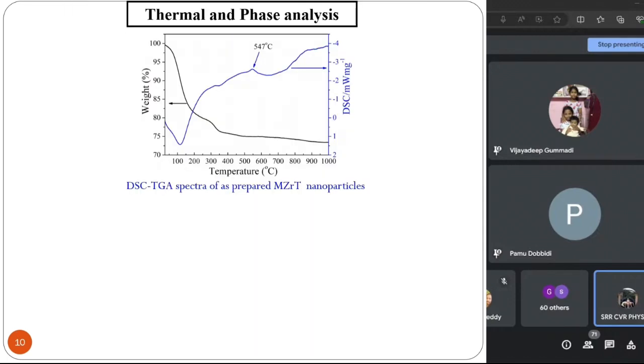Yeah. So whenever we start to process a material, because temperature is a crucial factor for us, we want to find out at what temperature this material crystallizes. You see that around 500 degrees C, this material is crystallizing from DSC TGA, and using that we have calcined this material to see the phase formation.